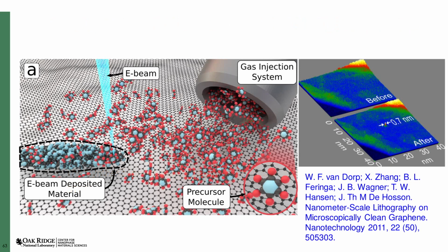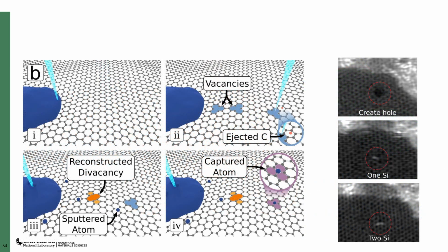We started with E-beam induced deposition. Van Dorp was able to push this technique to the physical limit, ultimately demonstrating molecule by molecule deposition. We also discussed why this technique can't quite get down to atom by atom deposition. To get down to single atom deposition, we have to abandon the operational principle of E-beam induced deposition. Instead of dissociating a precursor gas, we have to damage the substrate.